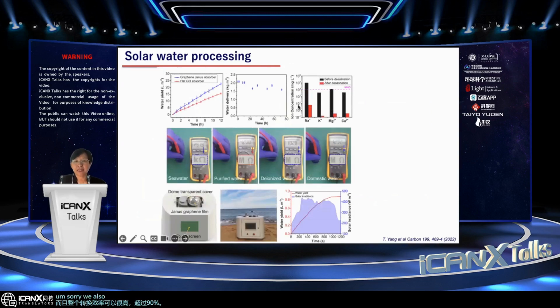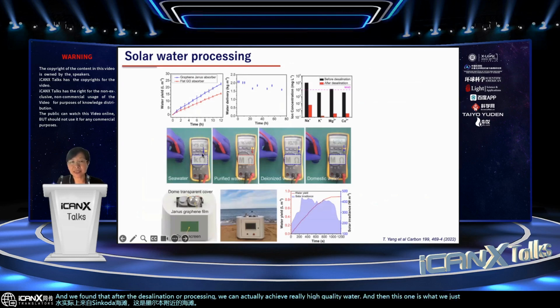We also measured the quality of this generated water and compared it to the WHO drinking water standard. The water is from St Kilda Beach, which is a beach just near Melbourne. And we found that after the desalination processing, we can achieve really high quality water. This one is what we generated, and this is the seawater, which is very conductive. That means it has lots of ions in it. And this is in comparison with deionized water and also domestic drinking water. Our one is actually quite pure.